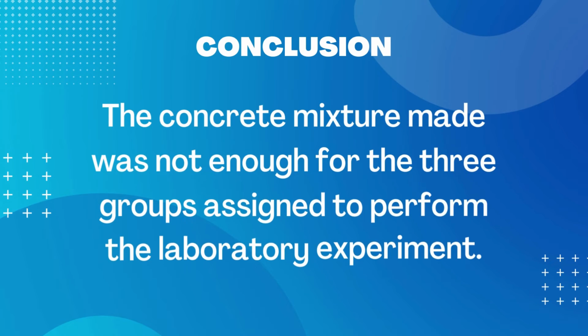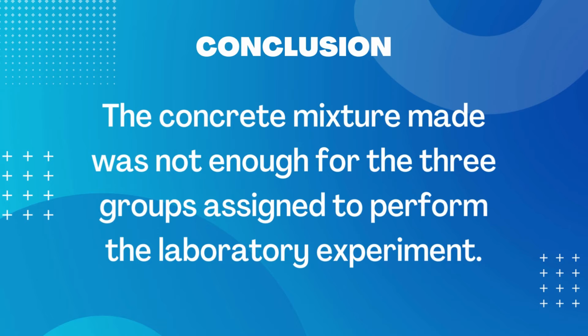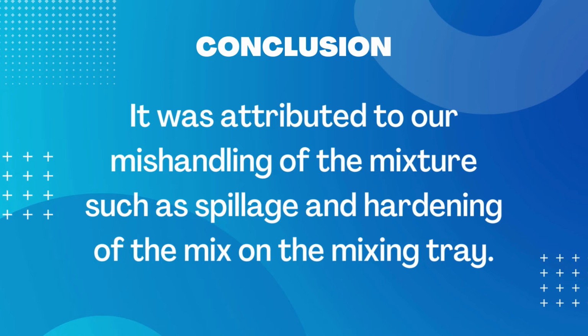After performing the assigned laboratory exercises, the group found out that the cement, gravel, and sand mixture was not enough for the 3 beams assigned. Thus, we only had 2 beams completely filled and 1 that was 7/8 filled. We concluded that such failure was attributed to our mishandling of the mixture, such as spillage and hardening of the mix on the mixing tray. Our group is inexperienced with mixing aggregates and cement, thus there were many mistakes along the way.